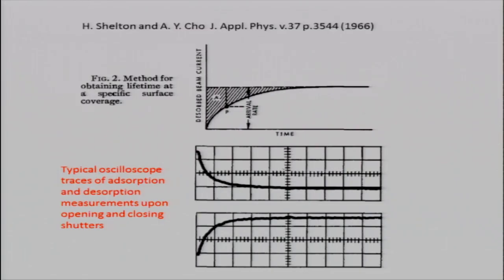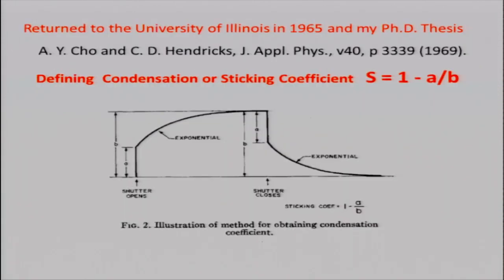As John Arthur alluded to earlier, when you open and close the shutter, you see the exponential curve on and off, and then by looking at the lifetime of that, you plot the Arrhenius plot. You get the activation energy of these molecules on the surface.